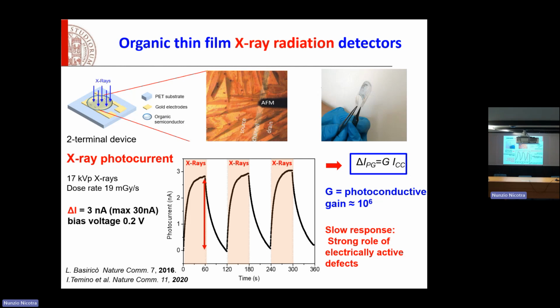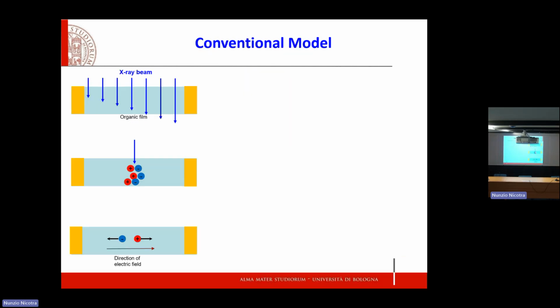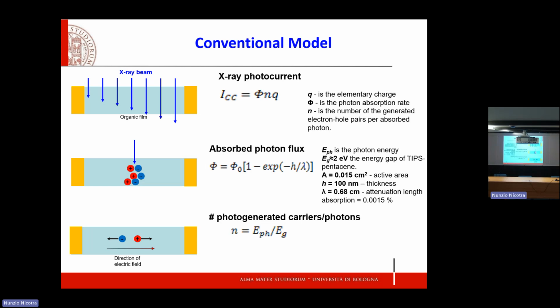But let us also comment on the relatively intense delta I that we measure. We are getting a strong signal out of a 100 nanometer thick organic material. How can this be? If we use traditional physics or traditional models for interpreting the generation of electron hole pairs, that means that the X-ray beam generates electron hole pairs, they get collected. Let's do the calculation of what we should collect in our thin film.